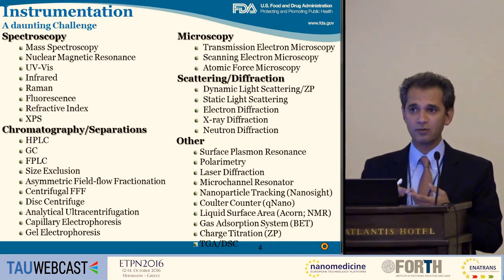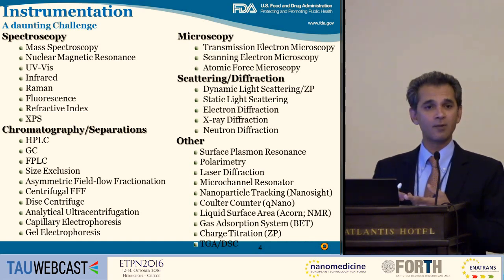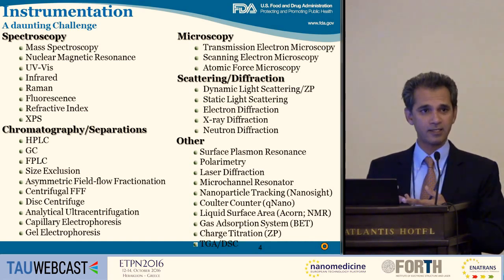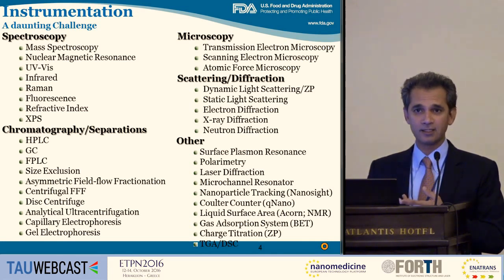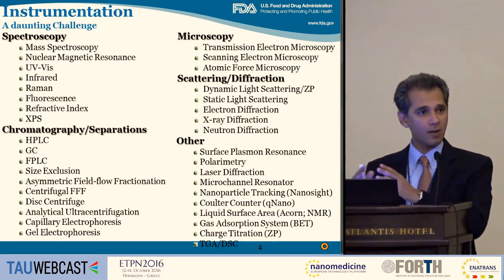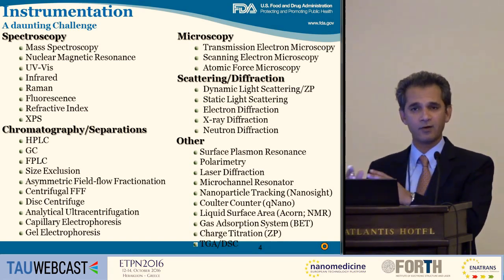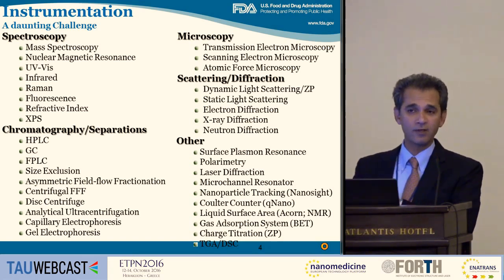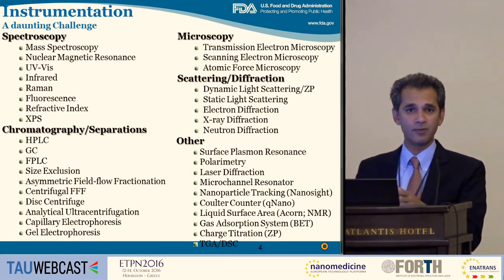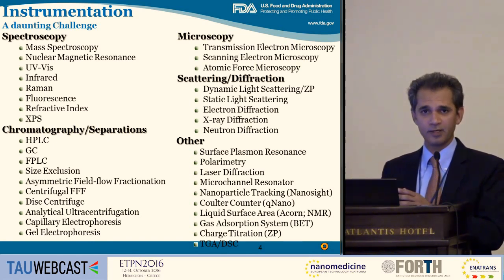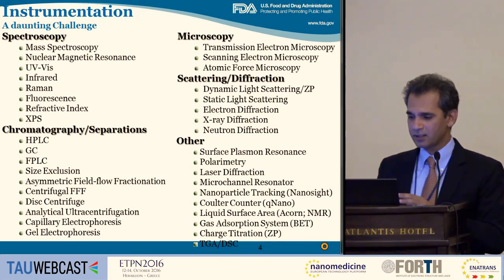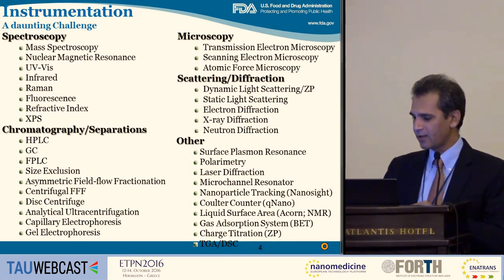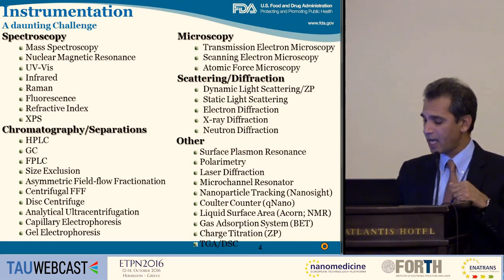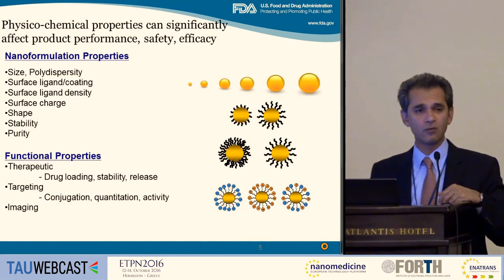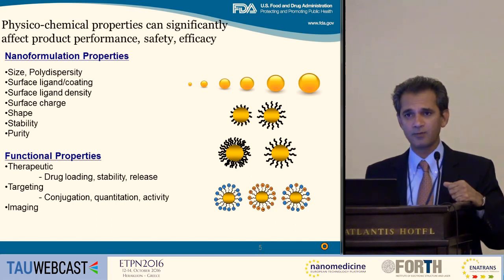So as you go, a lot of publications you will see a number-based measurements. For example, in dynamic light scattering, which is, from my perspective, useless, because you are essentially erasing the agglomerates that will have a biological impact. If you have larger agglomerates that are not counted, even if you have 5% of those in a number-based measurement. So you have to use appropriate methods to define those products using a more in-depth characterization. So this is, again, a daunting challenge for nano, but it's not to say that this size measurement is only one property.